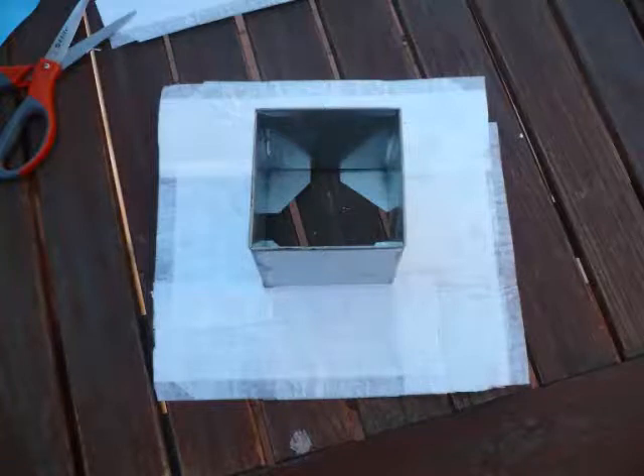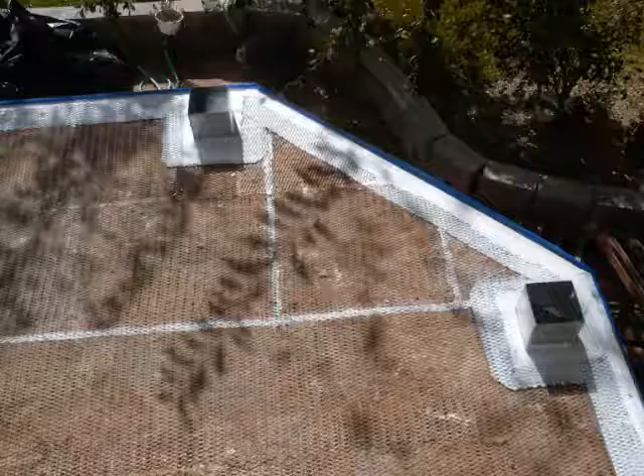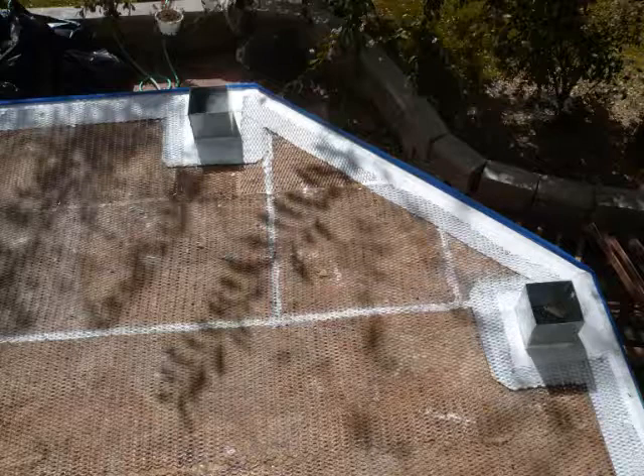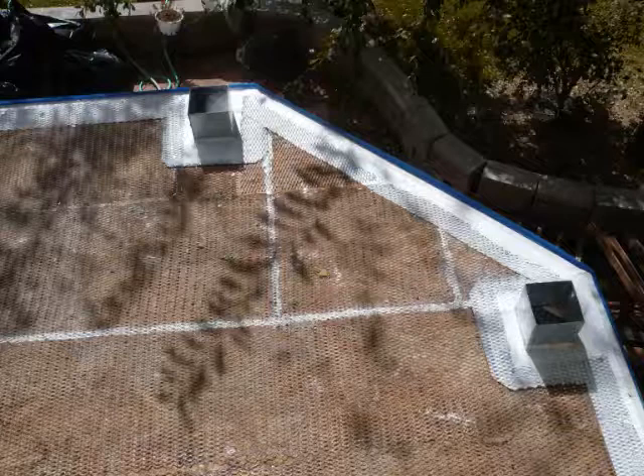The Super Seal tape laps may be overlapped 1 inch or butted in place. The Super Seal tape must be coated completely over all the fiberglass so as not to leave the fiberglass exposed to water. The Super Seal tape provides an easy solution compared to mechanical abrading and priming. The Super Seal tape is coating ready, and once it is installed, the coating may be applied directly over the top of the Super Seal tape.